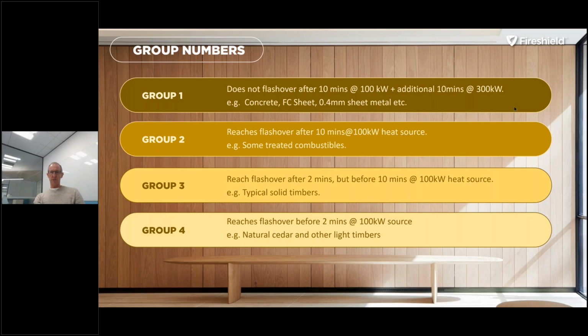So you can see that group 2 there reaches flashover after 10 minutes. At the bottom, group 4 was after 2 minutes, so already we've got quite a big difference. And it's only at 100 kilowatt heat source, whereas if you go up to group 1, it doesn't flash over after 10, which is the same as 2, but then we crank the furnace up to 300 kilowatts for another 10 minutes. And if it passes that, it's getting close to being equivalent to concrete or fibre cement sheet or even sheet metal. So it's a very onerous test. All materials go through the same, usually a 9705 or ISO 5660 test to achieve these.